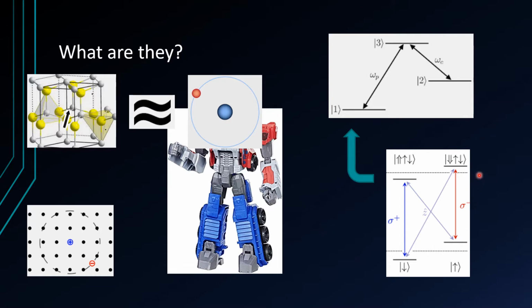Interfacing with the zinc oxide entails using one of the exciton states as a lambda system. You can initialize the qubit in 1 by pumping the transition between 2 and 3, which is one of the exciton states. Zinc oxide excitons decay very quickly, in about 1 nanosecond, to either of the two lower states with roughly equal probability. So by selectively exciting the 2 to 3 transition, you will eventually end up with all 1. Readout is performed similarly, for example, by selectively exciting the 1 to 3 transition and waiting for a photon. If you get one, regardless of what color you get, the measurement result is 1.